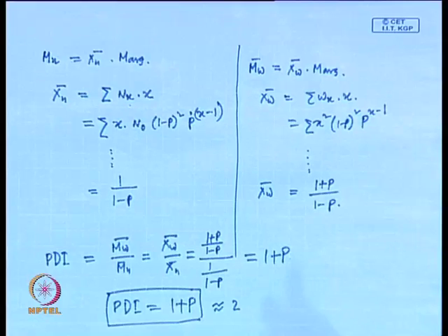So, you cannot make step polymers of high molecular weight where the PDI is narrow, 1.2 or 1.3. That is not possible, because remember, to make a high enough molecular weight you need r equal to 1, close to 1, so p is close to 1.